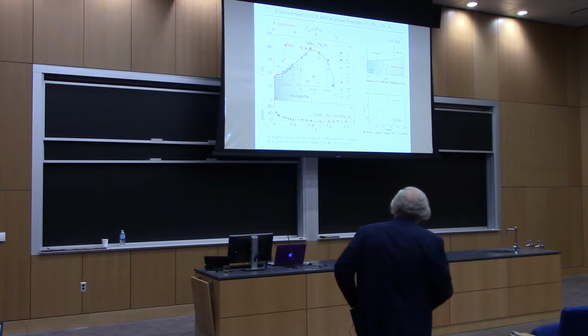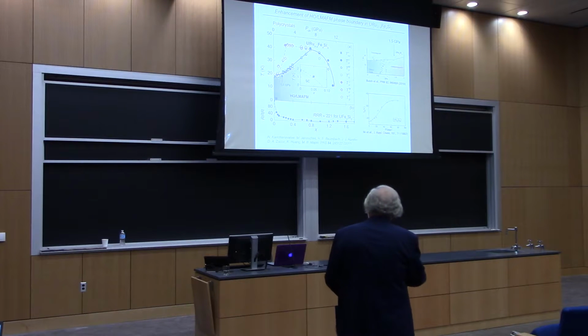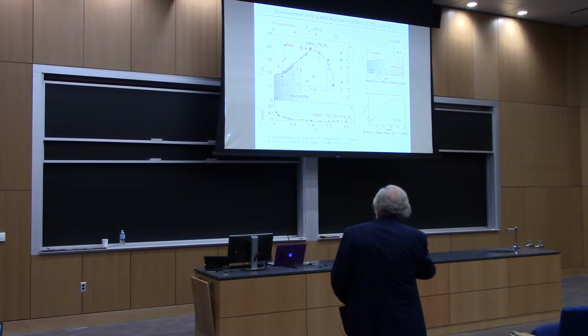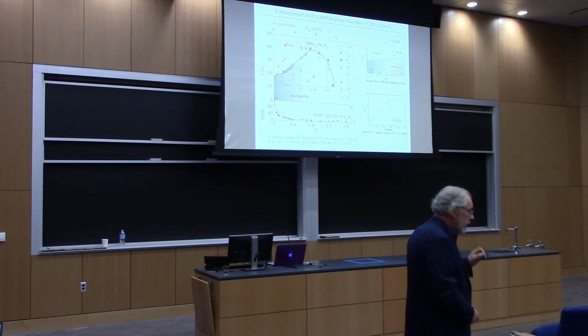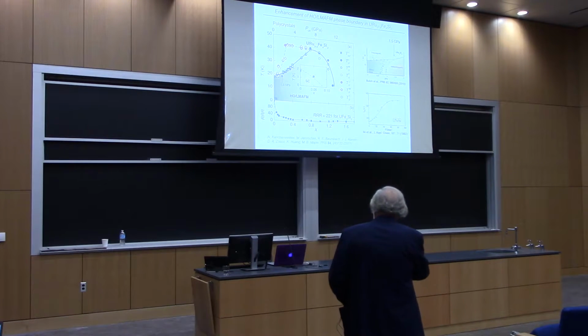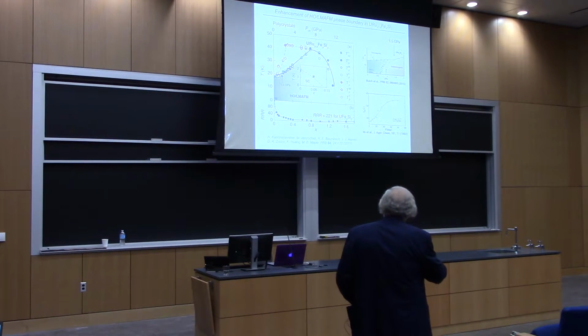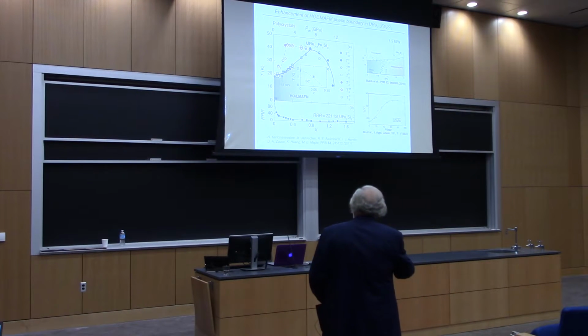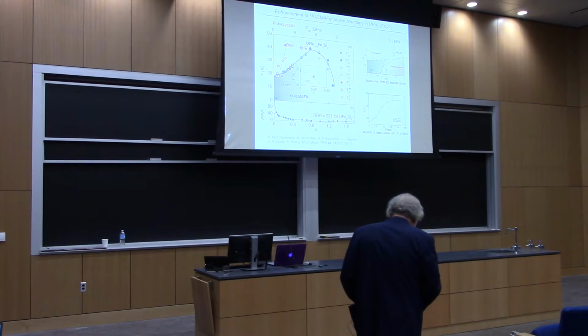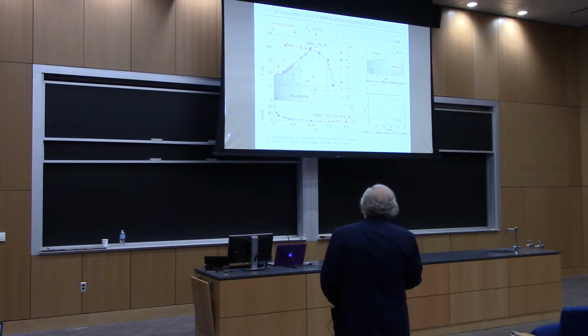And then the phase diagram based upon polycrystalline material, which involved a lot of work, is shown here. This is temperature versus iron concentration, and you see these red points are very small features that are spurious. They're only in the polycrystalline materials, so you can disregard them. What you see here is that this phase boundary looks very similar to the phase boundaries under pressure. I showed you this peak before for low pressures, and then for higher pressure it goes to a maximum, which is shown here. A similar thing happens here. There's a kink that occurs at a volume that corresponds to a chemical pressure about the same as this pressure right here, around 1.9 GPa, and then it goes up to a peak. This is based upon resistivity, magnetization, and specific heat at various points.